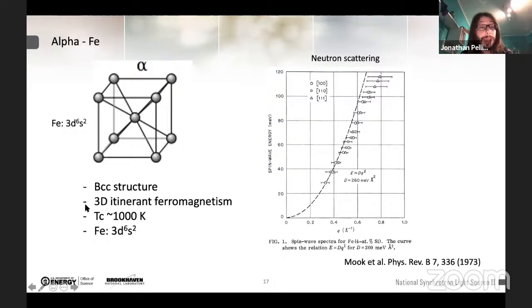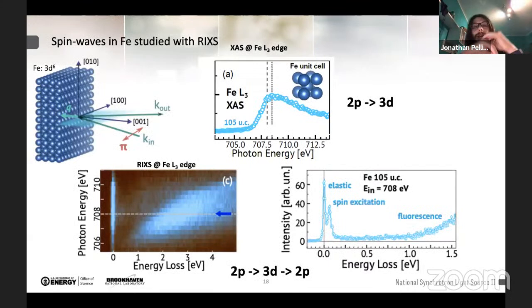a 3d6 4s2 configuration. And the spin excitations of iron were measured by neutron scattering a long time ago, back in 1973. And it was shown that the bandwidth and spin excitation energy are isotropic along the three crystallographic directions, and follow a quadratic path. And in our study, we selected iron as a benchmark to understand what we can do with RIXS in this material. And normally, when you start a RIXS experiment, the first step is to collect X-ray absorption.